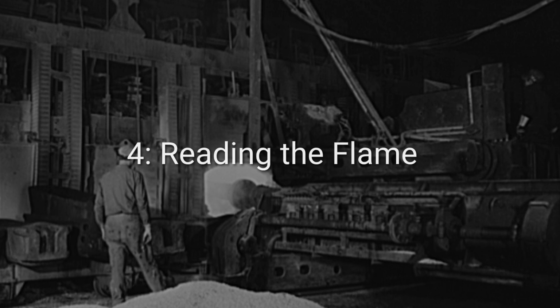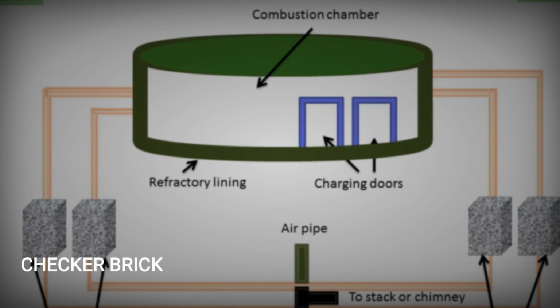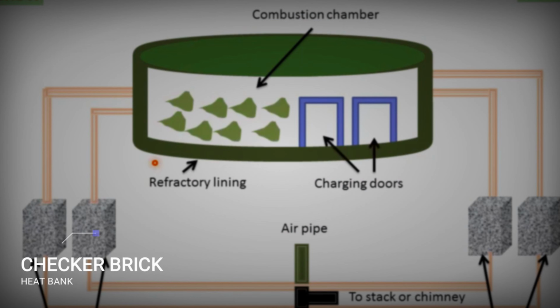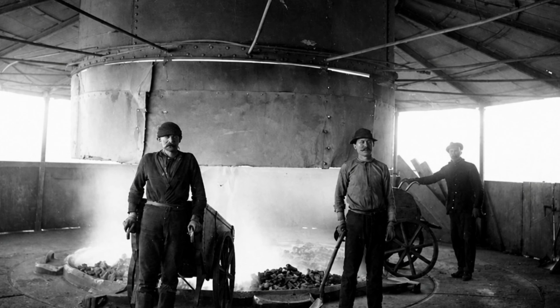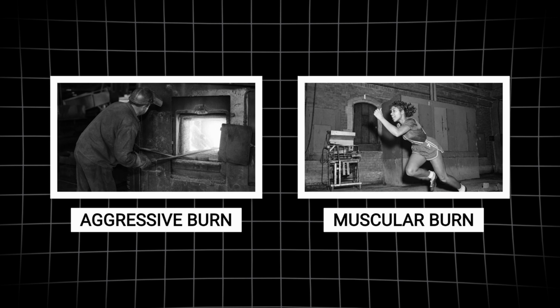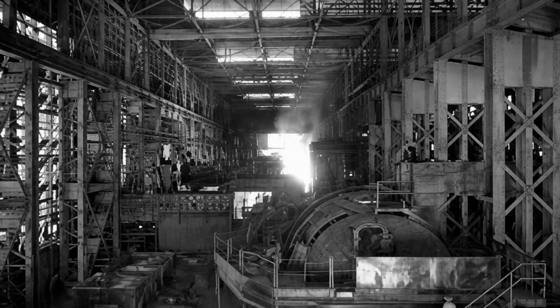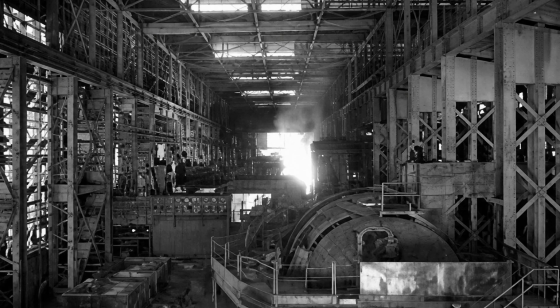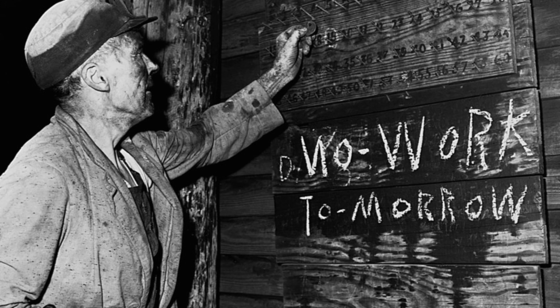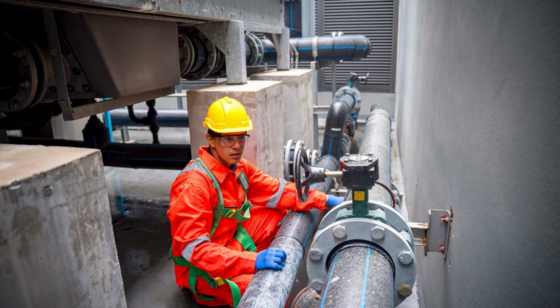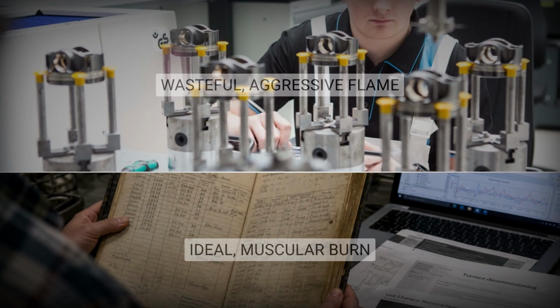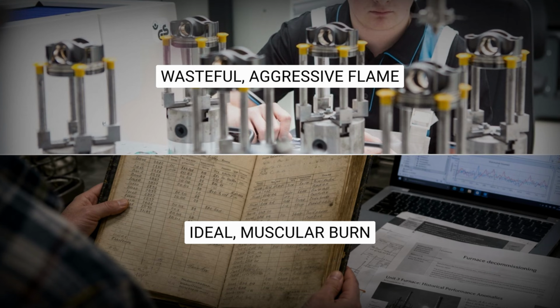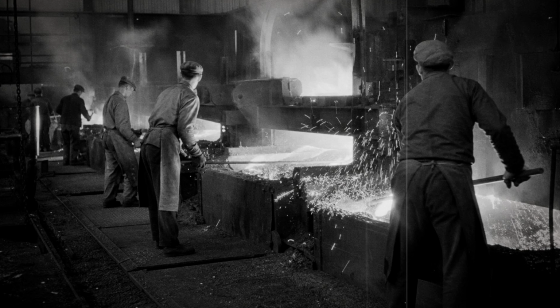Every 15 or 20 minutes the furnace reversed, air and gas swapping ends to reclaim heat from checker brick. And the melter timed the reversal by the sound of the burn and the color at the ports, keeping the furnace breathing like a long-distance runner. Get the rhythm wrong, and heat slowed by hours, and hours were thousands of dollars. Combustion is fully computerized now. Oxygen probes, flow meters, optimization software. Engineers who tested the software against records of the best hand-fired furnaces of the 1950s found something uncomfortable.